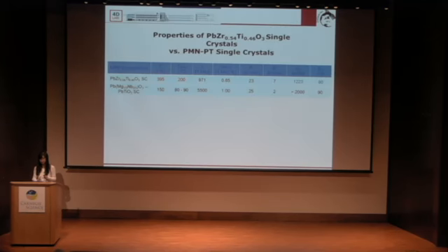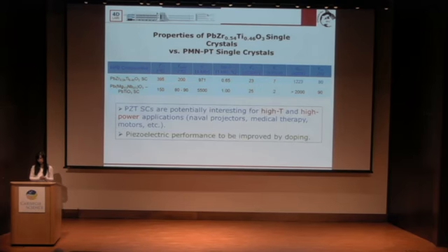And compared to the PMN-PT single crystals, even though the d33 and k33 values are a little bit lower, PZT single crystal has a much larger coercive field and higher phase transition temperature. So it is potentially interesting for high temperature and high power applications.